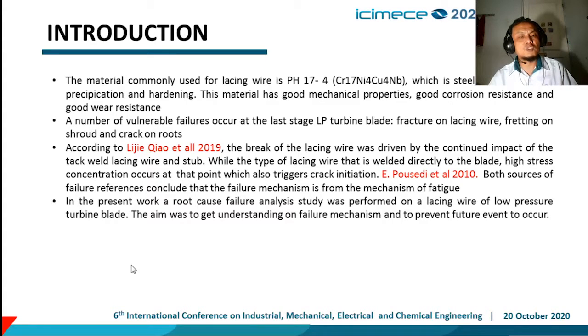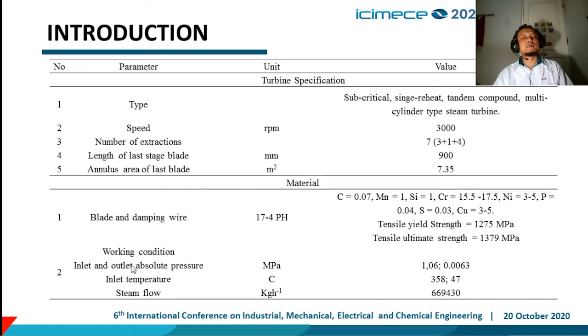In the present work, a root cause failure analysis study was performed on lashing wire of low pressure turbine blade. The aim was to get understanding of the failure mechanism and to prevent future events from occurring. This is the object of study: a low pressure steam turbine with a speed of 3000 rpm, and length of last stage blade is 900 mm. Working condition inlet and outlet pressure is 1.06 and 0.0063 MPa. Inlet temperature is 358 Celsius.